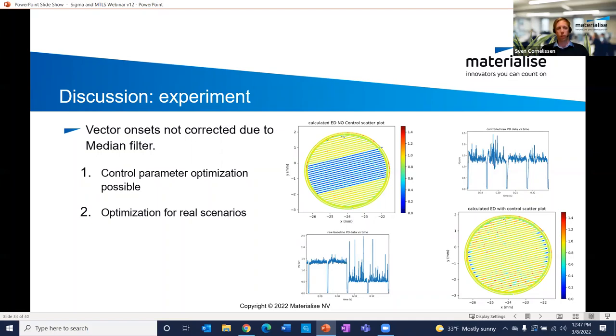chose our control parameters. And I think the main thing to remember here, of course, is this experiment is very artificial, right? So we're inducing in a stepwise manner local regions with a reduced energy density, which is very nice again for showing the power of closed loop control. That, by the way, you get out of the box with this combined Materialise and Sigma Labs system. And so you can really show the power, but you can't really expect that for the nominal conditions, the same control parameters would work well. So one of the questions is, is this a real scenario, right? And are these the control parameters that we should choose?